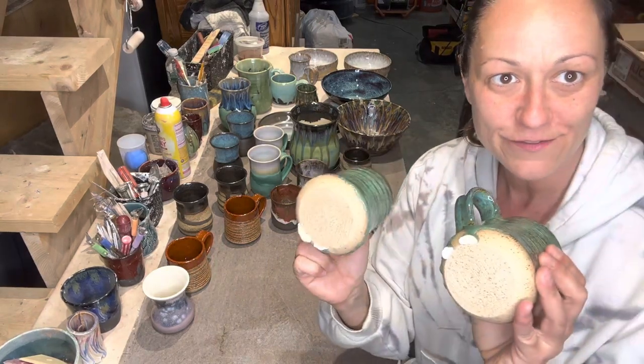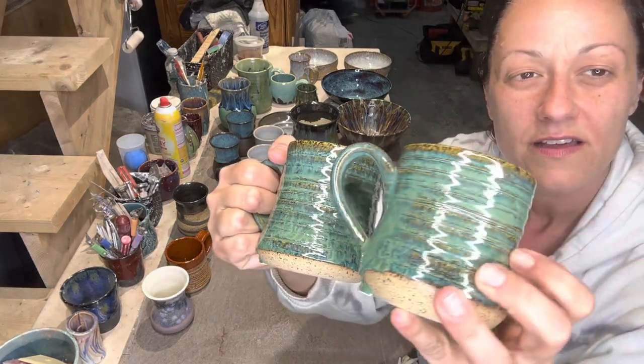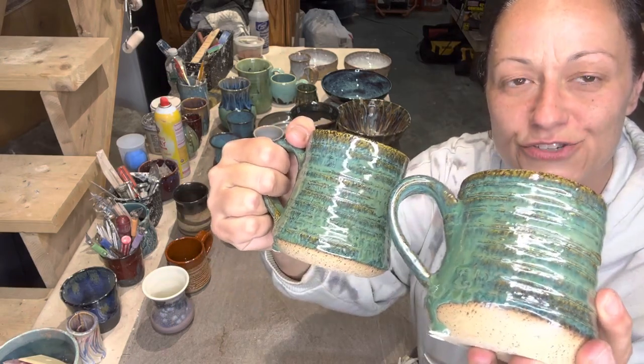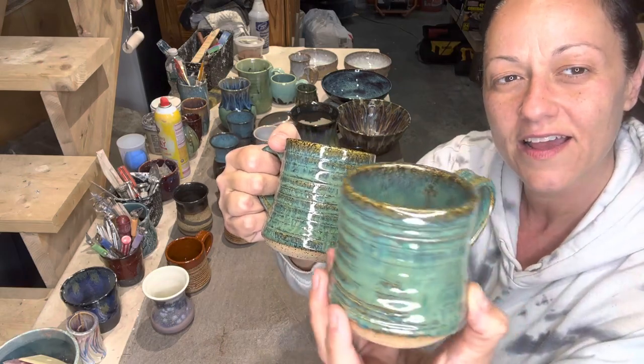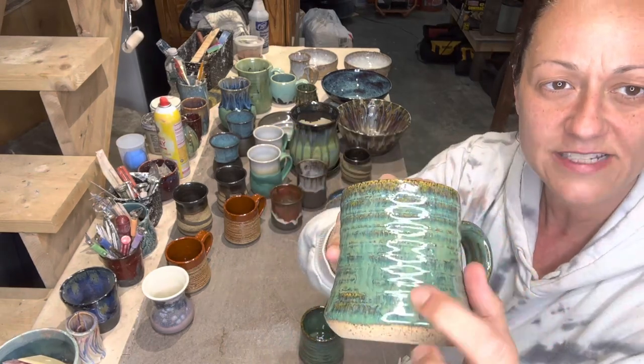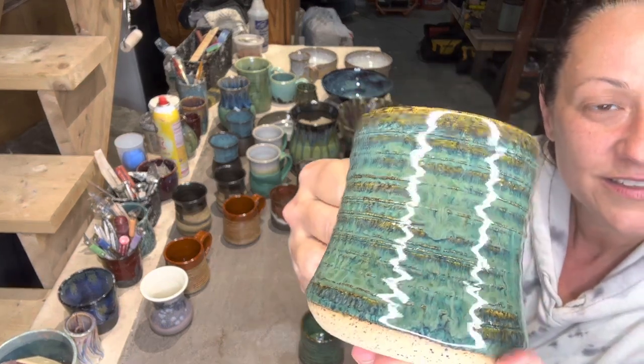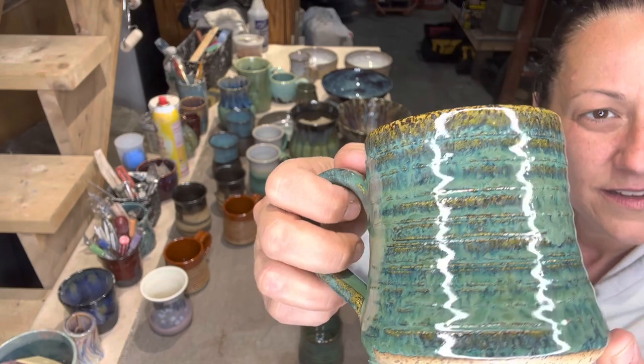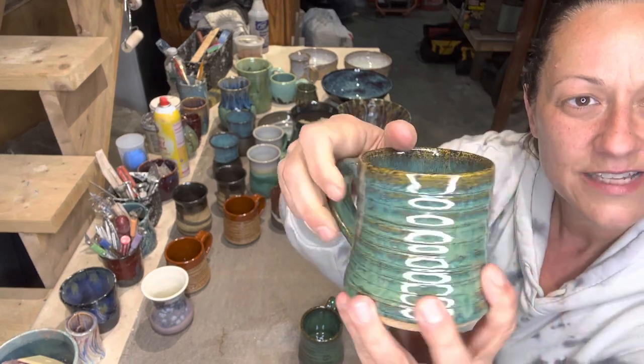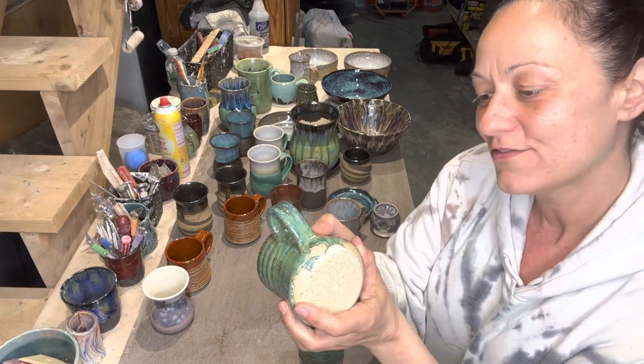These stuck — the bottom shelf got the hottest. On speckled buff, I did three times of emerald falls and then two times of textured turquoise over that. I've done this combo before but not with texture. I tried it on texture and I like it better because see how it breaks — it just adds more depth to the piece. We'll have my handy dandy husband fix these drips.